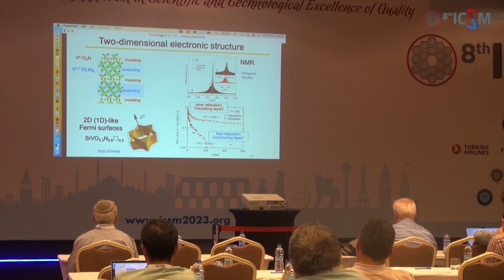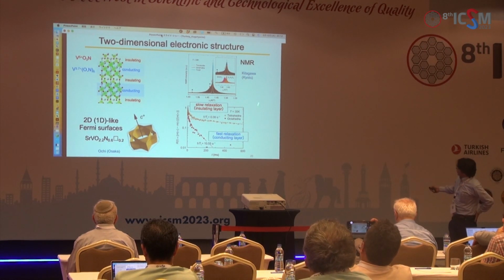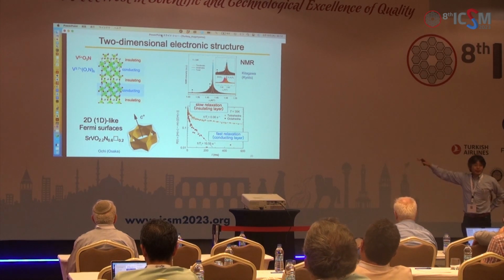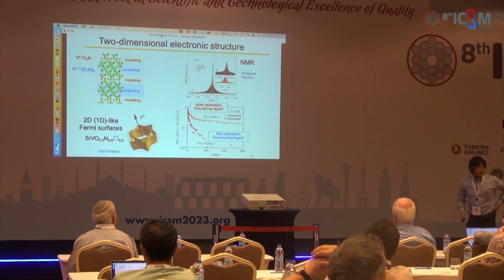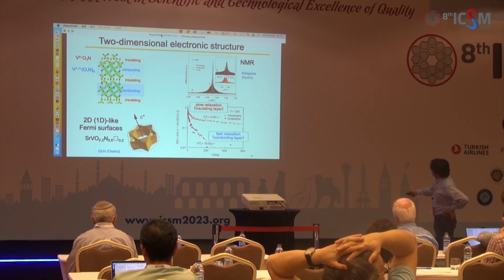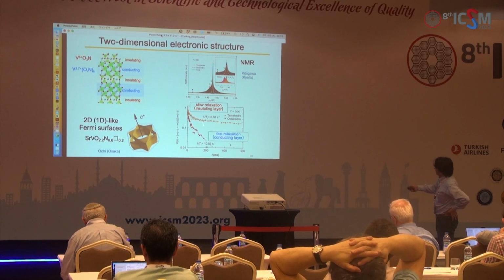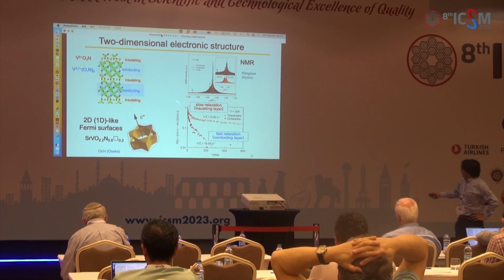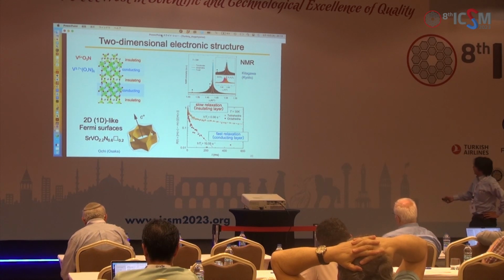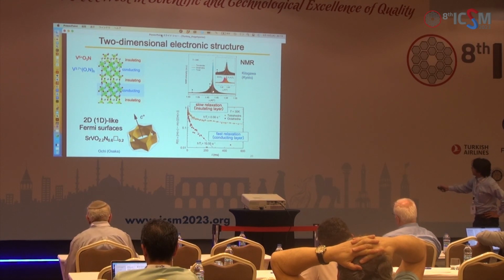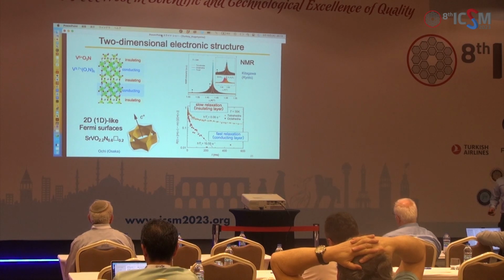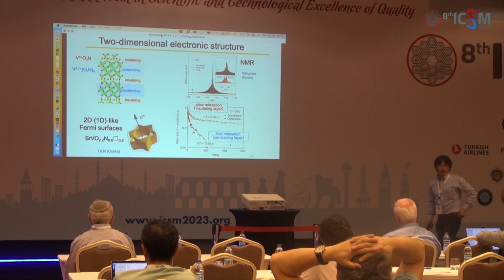Then, in fact, there are several experiments, such as NMR measurement, showing that this material is a very good two-dimensional conductor. This is the relaxation time. You have this vector that can be decomposed into two parts. One shows very rapid decay, showing that this should be the conducting layer. Another one, this sharp one, has a very long relaxation time, meaning that this is based on the vanadium 5+ in this insulating layer. And the DFT calculation made by Ochi at Osaka University shows two-dimensional-like cylinder-type Fermi surfaces.